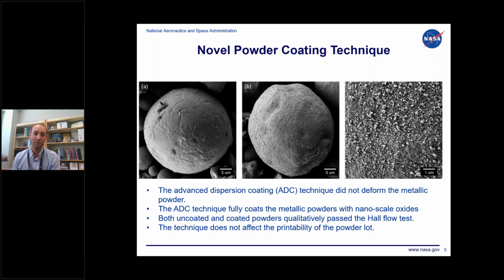When you try to 3D print that type of powder, you really introduce a lot of defects into the part because it's not a very spherical powder for 3D printing. In this case, however, we don't deform the metal powder particles, and in fact what we have found is that the flowability appears to improve significantly after we coat it. So this coating process is really amenable to the 3D printing step.